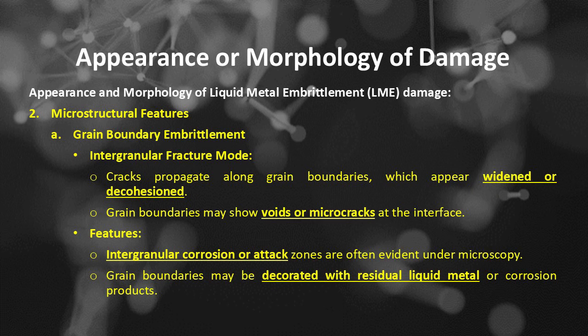The appearance and morphology of liquid metal embrittlement, LME, damage. Number 2 is microstructural features, includes number A, grain boundary embrittlement, includes intergranular fracture mode: cracks propagate along grain boundaries, which appear widened or decohesioned. Grain boundaries may show voids or microcracks at the interface. The features of grain boundary embrittlement are intergranular corrosion or attack zones, often evident under microscopy. Grain boundaries may be decorated with residual liquid metal or corrosion products.